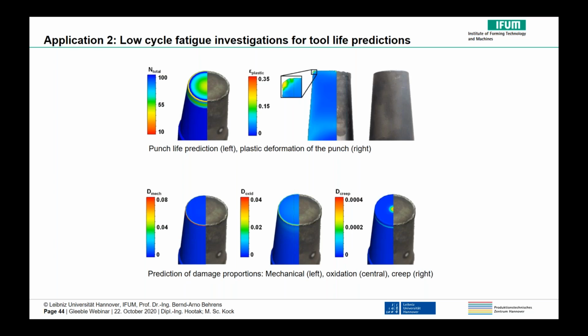Afterwards, a cup backward extrusion process was investigated. The figure shows the numerical and experimental results. By comparing the punch in its initial state with a worn and deformed one after 20 cycles, it is evident that relatively high degrees of deformation of the tool material occur due to the high heat input, accumulating from cycle to cycle. This leads to decreased yield stresses and thus to plastic deformation, which simulation could predict in advance.